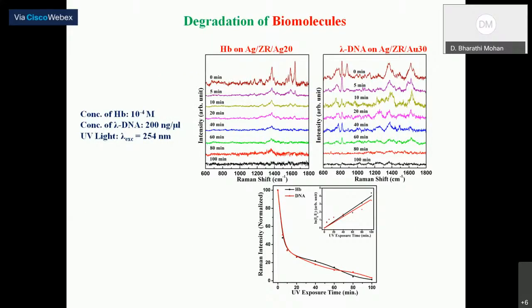The degradation study is again done on these biomolecules. So we tested with hemoglobin as well as with the lambda DNA, and you can see very clearly that when the degradation time increases, the Raman modes of the hemoglobin and the lambda DNA get suppressed, and they completely disappear after 100 minutes of degradation time. And the degradation constant is again calculated for these two, and it is found that silver is offering a better degradation constant compared to the gold-based nano substrate.